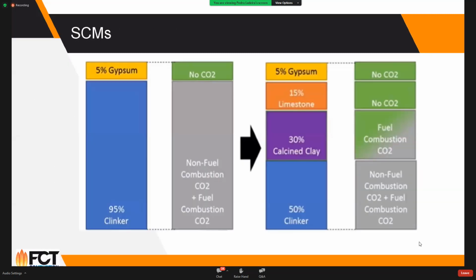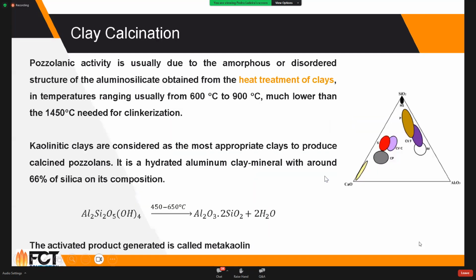So when we go into looking at this calcined clay, that can be a big chunk of the reduction. We look into synthetic pozzolans. Hopefully, I wish we had natural pozzolans all over the place, but we do not have it. So we get material, when we heat treat it, the clays, and fortunately, the temperature they need for the dehydroxylation ranges from 600 to 900, which is relatively low, and you can produce nice metakaolin out of it. So instead of producing C2S, C3S, we are producing AS2, a good substitute, which has low to no CO2 coming from the raw material.